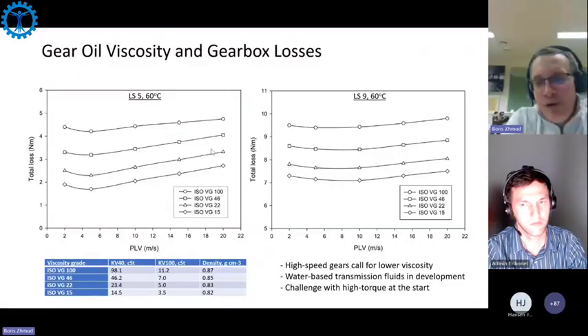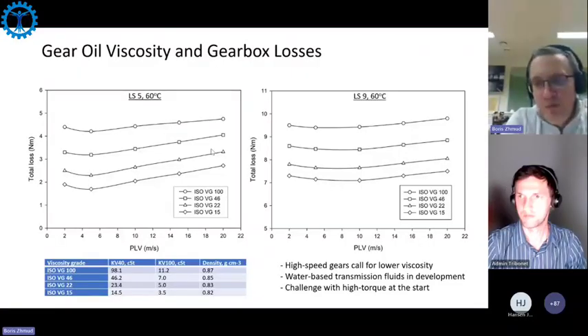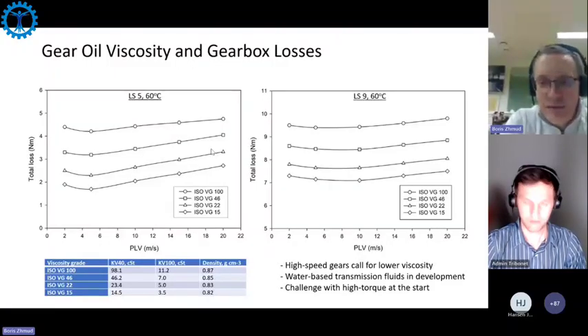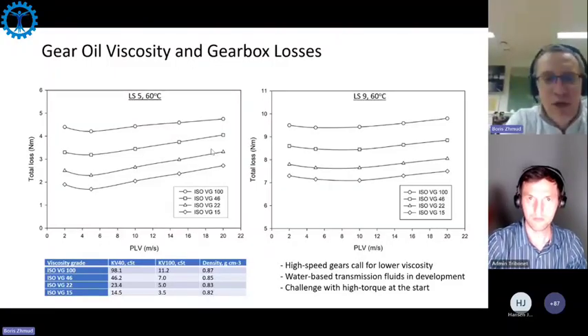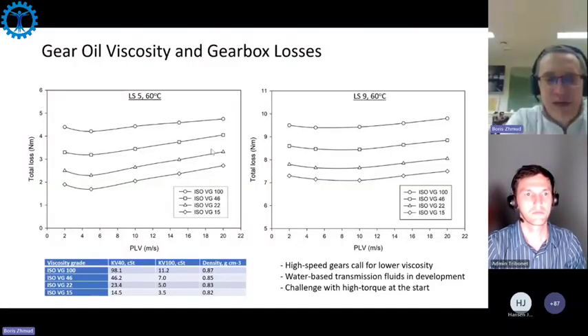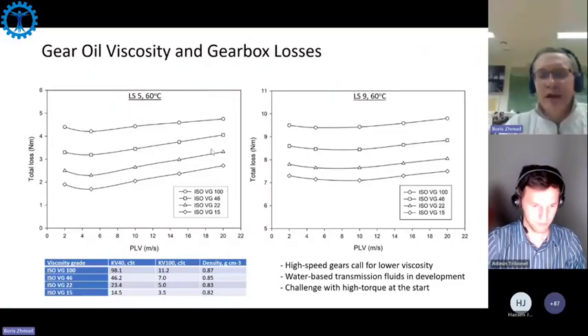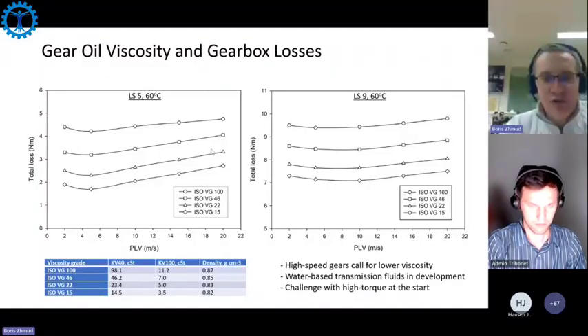We moved from group 2, hydrotreated group 2 base oil, to fully synthetic polyalpha-olefin based, and as you can guess from viscosity 3.5, it is actually an Exxon base oil. What was used in this case is fully PAO based.